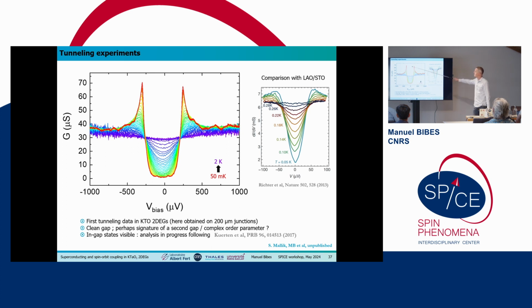So this is a very nice, I mean, for us, for this oxide 2-deg community, nice gap. This is the best data that was reported in the case of LAOSTO. So we see here we are able to see really zero conductance at the bottom here. This is, of course, because the TC is much higher. It's about 1 order of magnitude higher.